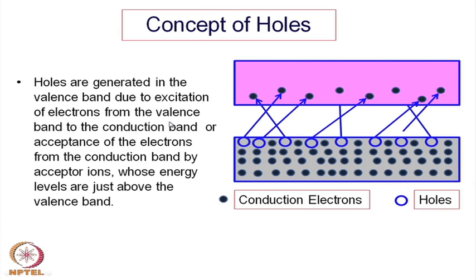In any semiconducting system where there is a band gap and there is an excitation of the electrons from the valency band to the conduction band, holes will be created, and holes are almost equivalent to the electrons, except that they have a positive charge rather than a negative charge as in the case of electrons. So, they can also have mobility.